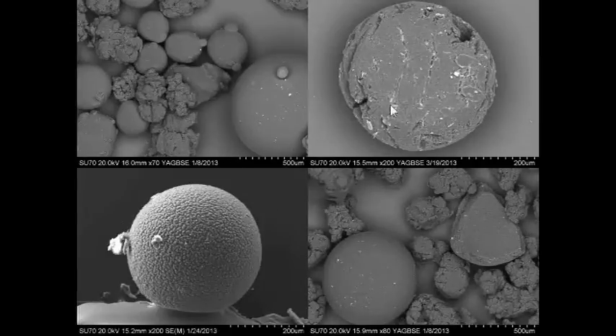And this is just a visual comparison. These last two images are of beads that we found in the Great Lakes, compared to those that we took out of the beauty products. And we see that there's definitely some comparison. These were both blue beads. The bottom two images were both blue beads. This one was from a product that we took off of the store shelf. The left one is a blue bead that we found in the Great Lakes. Elemental analysis for these two matched up very nicely in that they both use cobalt to produce that nice blue color, as well as some other inorganic substances for the coloration. So you can essentially use the color of the material to provide a fingerprint for their possible sources.